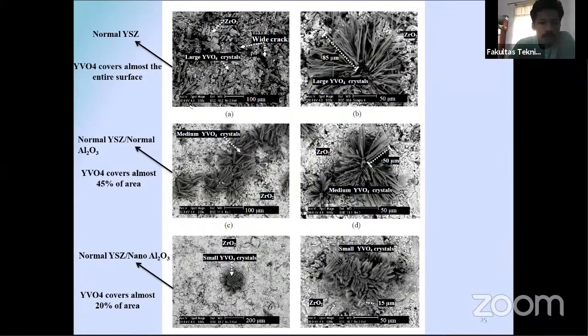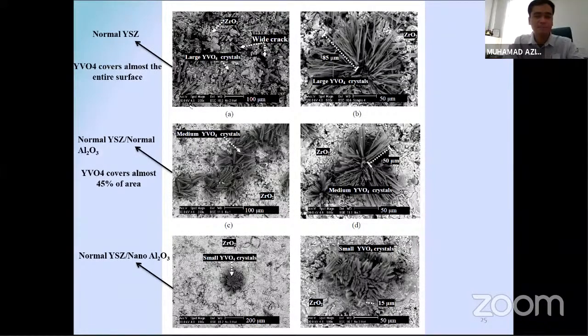So in the presence of the salt, the yttrium reacted with the vanadium and the impact is maybe the quantity of the yttrium has decreased in the thermal barrier layers. Yeah, exactly. You lose the structure.